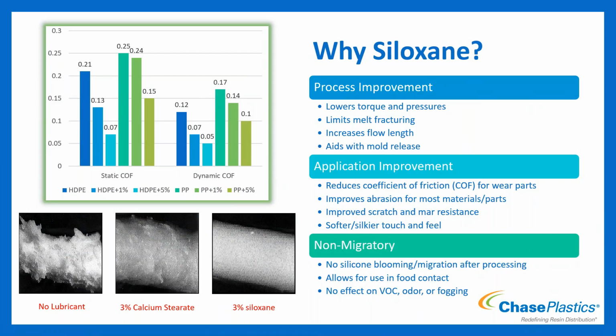It improves your abrasion and scratch and mar resistance for most materials. So if you've got maybe your dash in a car or the side door and it's prone to getting scratched, maybe it's a talc-filled polypropylene or something like that, a siloxane or slip agent in there could help so it's not going to scratch as easily. The other nice thing is, again, if you add enough in, it gives you a softer or silkier feel. So maybe that's something that you want out of your part. It can do that if you add some of it in. And then lastly, it's not migratory. I think a lot of people tend to think it migrates a lot. It's already at the surface. It doesn't migrate after you process it. So once it's solidified, it stays there.